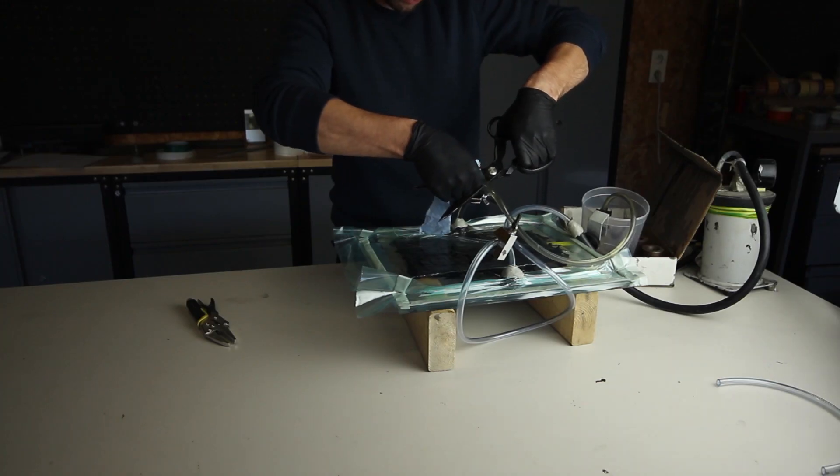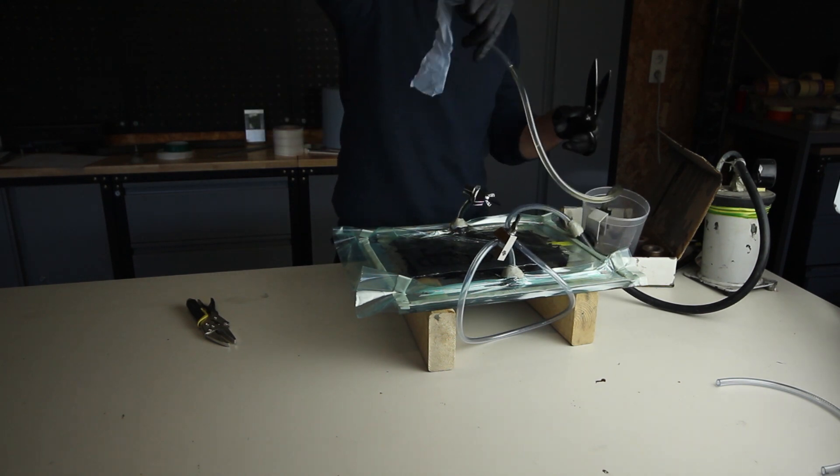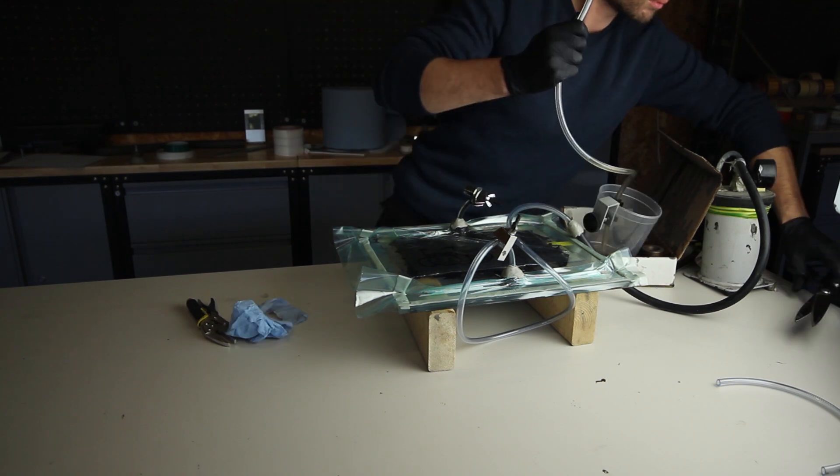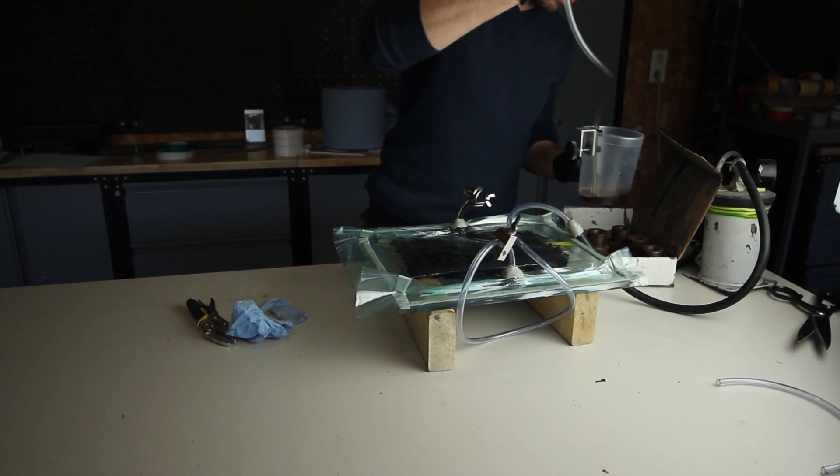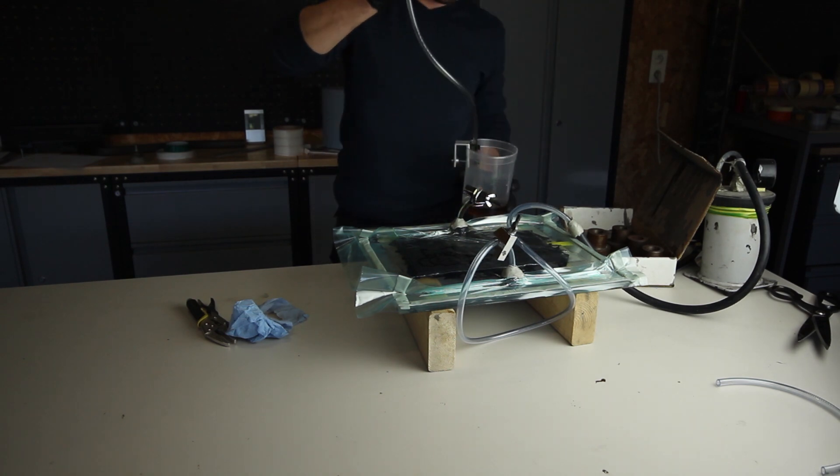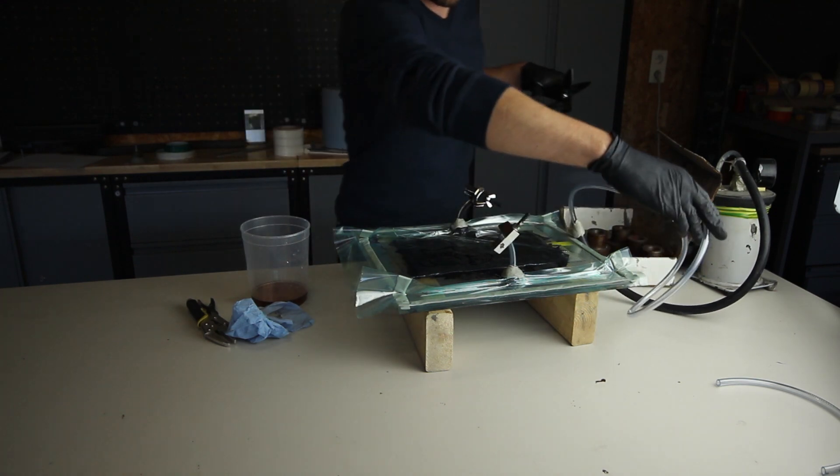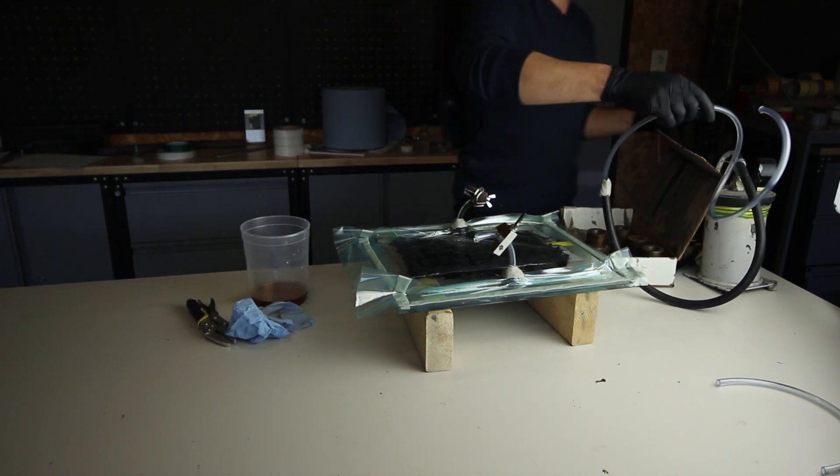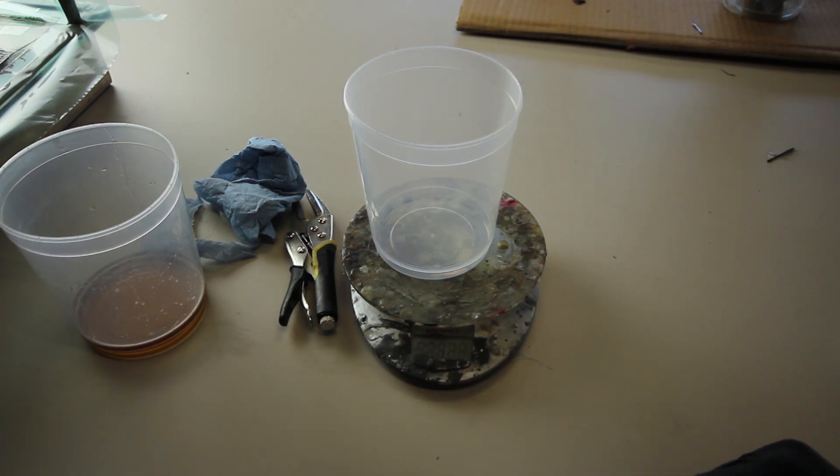Here you can see me closing the infusion. Keep in mind that polyester resin has a low boiling point, so under vacuum the polyester resin will start to boil. What I did is leave the resin line open a bit longer after closing the vacuum side so we can know how much resin went into the parts.